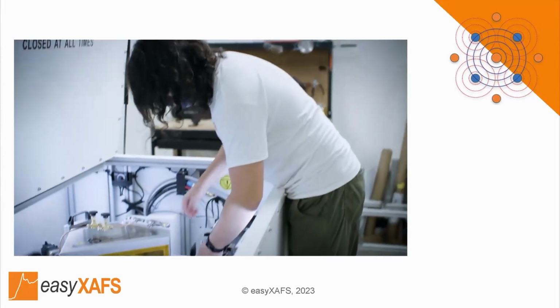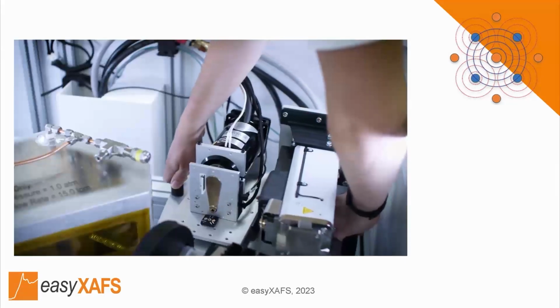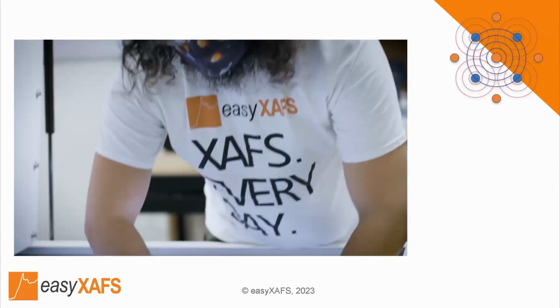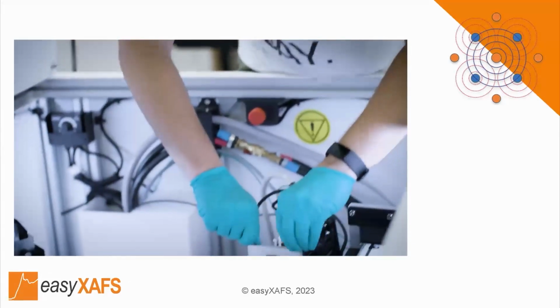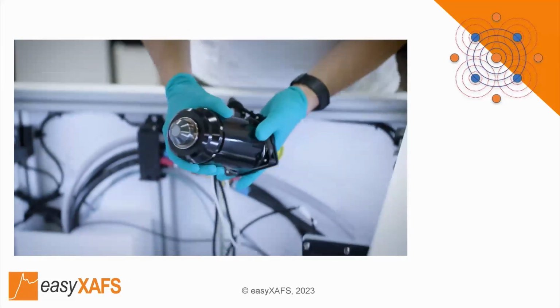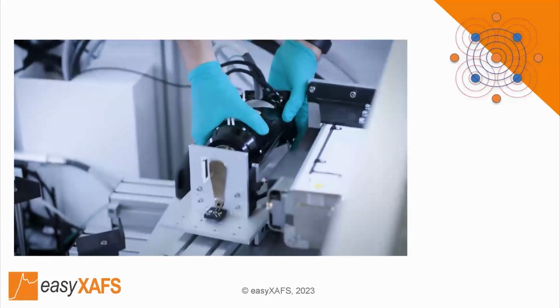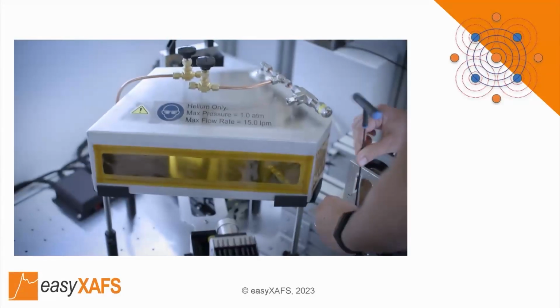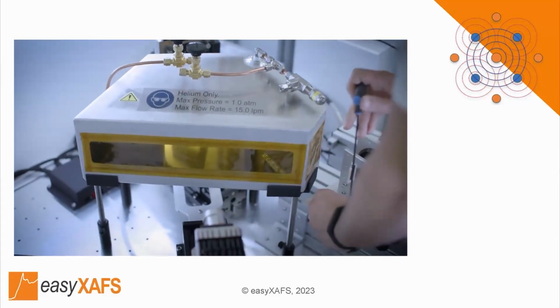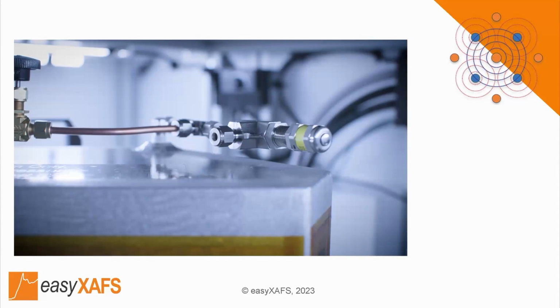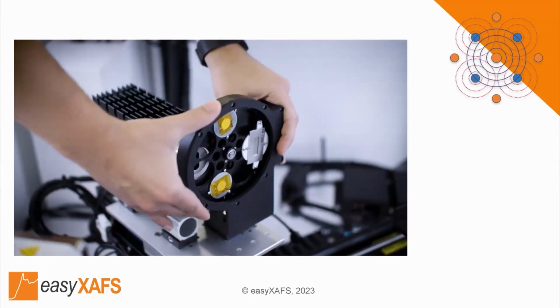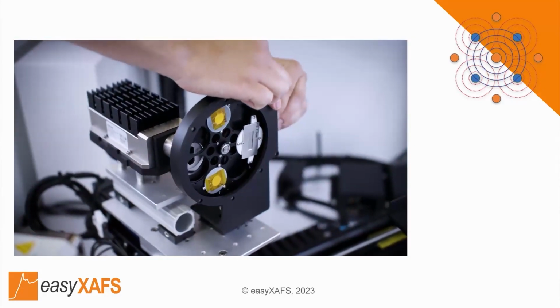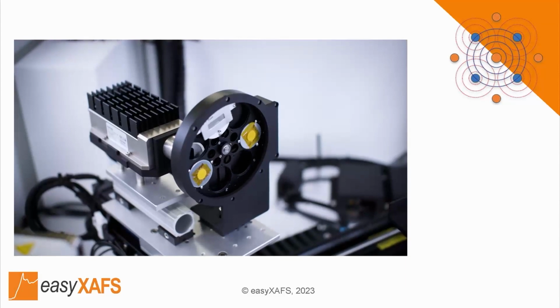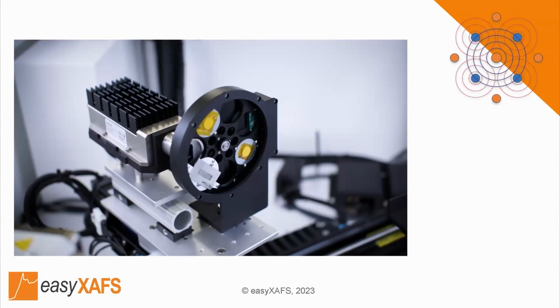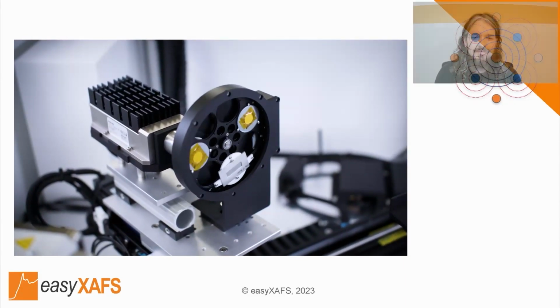This is used in our 300 level spectrometers. Commercial XRF style tubes are used for X-ray emission measurements. These tubes allow for minimum distance between your sample and beam spot, providing maximum flux for XES. A helium flight path is employed to reduce air absorption and improve flux at lower energies. Our automated XAF sample exchanger allows for programmable studies, so you can set up a series of scans to run unattended. Let the data collect while you're away.